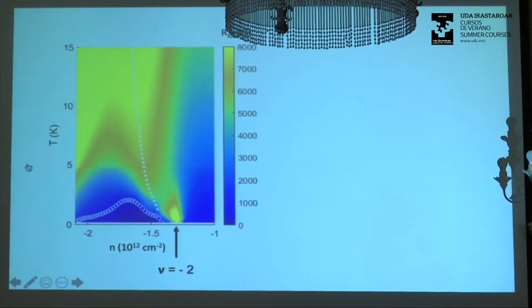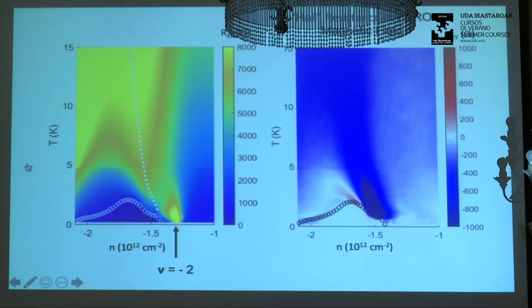this is measured in a Hall bar geometry. So we can now do the equivalent of a Hall measurement, except that it's going to be at zero magnetic field. So I'm just going to measure the resistivity in the transverse direction. Okay? I expect to see zero because there's no magnetic field. Okay? But this is what we see. If you measure the Hall, a Hall in quotes, because it's at zero magnetic field, just a transverse voltage, Hall bar versus temperature and density, you see this very prominent feature. I'm just laying this line on top here in this axis without modifying it. You can see that it happens exactly where we have this feature here.